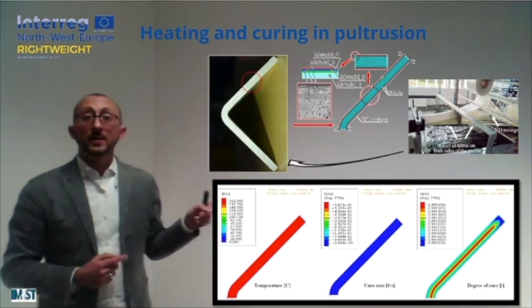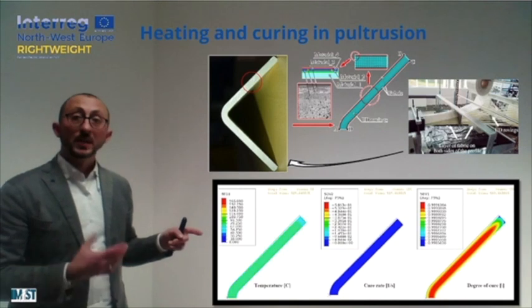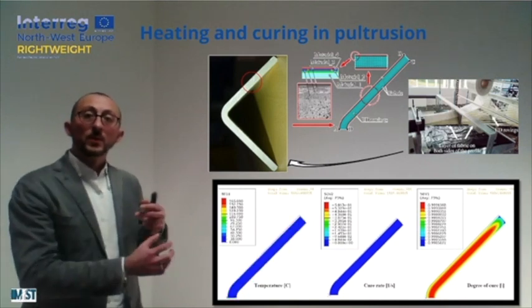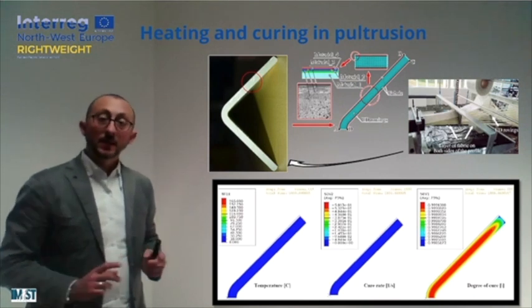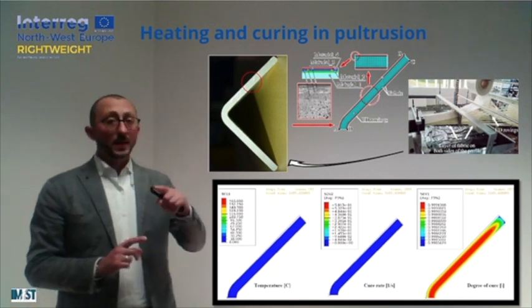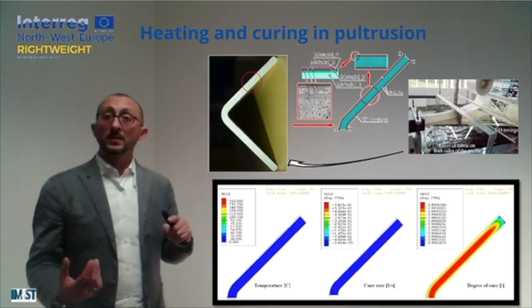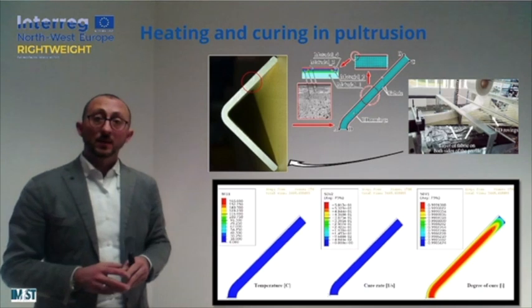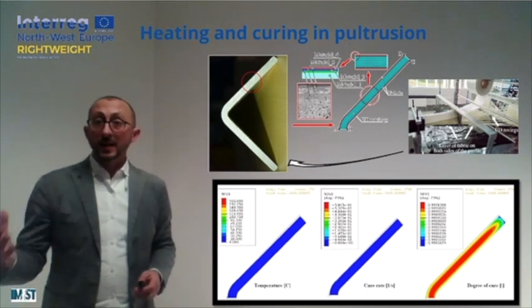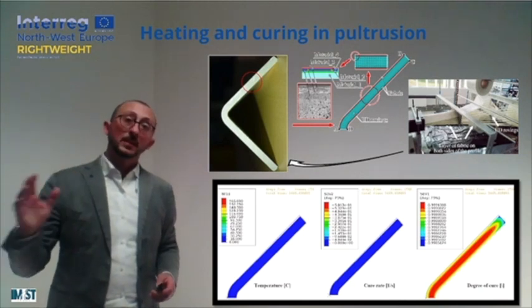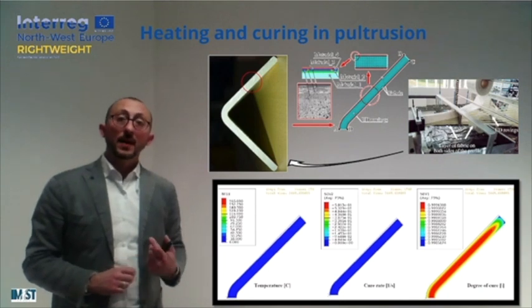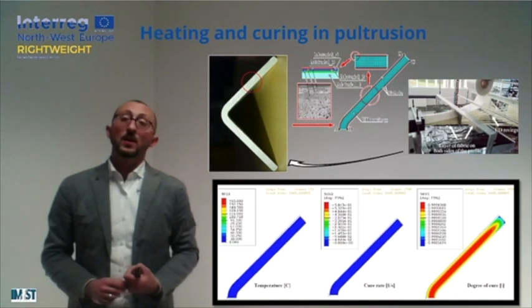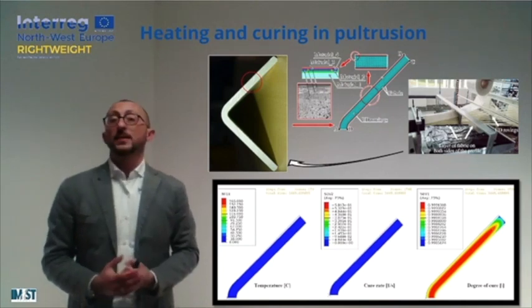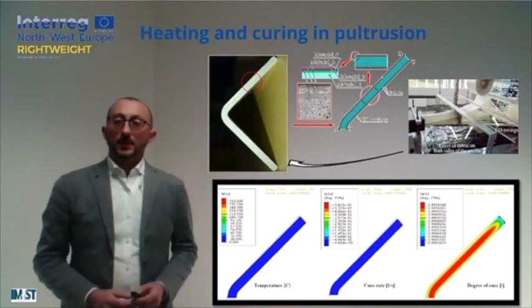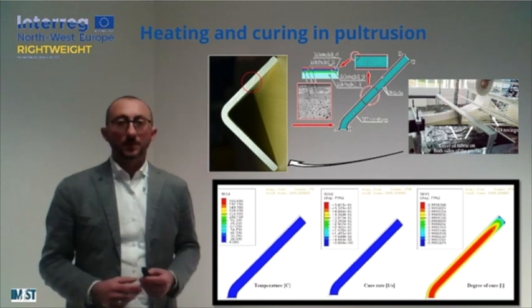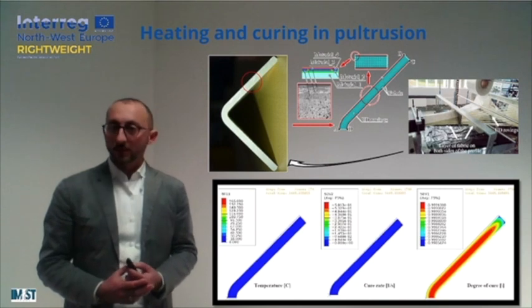But after a while, when the reaction will be activated also at the core of the material, the situation will be completely reverted, meaning that the temperature inside the material will overcome the temperature at the surface, and this is referred to as the temperature crossover point, and the same thing will happen for the degree of cure. Higher at the beginning of the process at the surface, but after a while at the cure crossover we will have higher values of the degree of cure at the core of our composite, and clearly lower values on the surface. The proper definition of the processing parameters, anyway, is not just a matter of temperature and degree of cure.